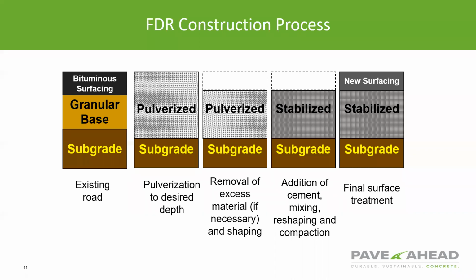And then after the pre-pulverization, if you have some grade restrictions that you have to adhere to, then you can remove some excess material, or it could be pre-milled ahead of time with a mill before you do the pre-pulverizing. It just depends on the job conditions.